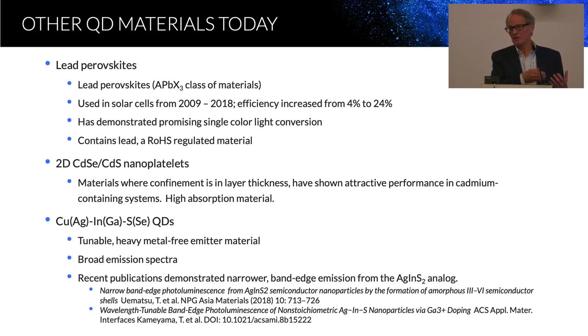Again, it's very hard to translate this work to cadmium-free systems, but ultimately that needs to be found. And then a very interesting system, for those of you that are familiar with solar, there's a material system called CIGS, copper, indium, gallium, sulfide or selenide. And then there's an analogous system which has silver instead of copper. The problem with the copper-based system is that it's tunable, it's a good emitter, but it has a really broad absorption, far too broad to be useful as an emitter. But recent work from some Japanese groups shows that they've been able to take the silver analog and get a fair amount of band gap emission. It's not perfect yet, there's still a lot of this broad emission too, and the quantum yields aren't that high, but it's an interesting direction for further study.